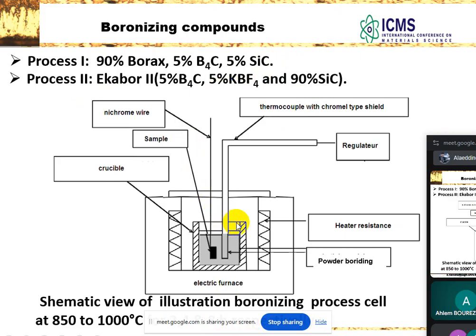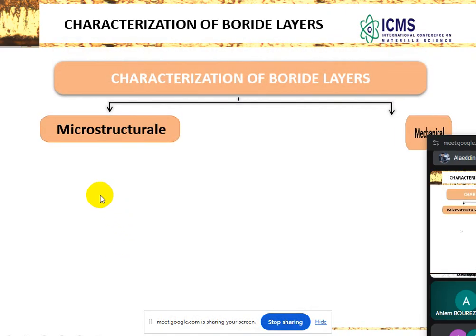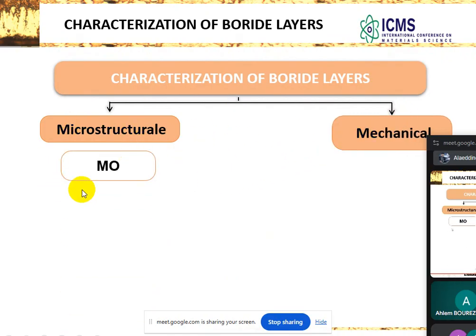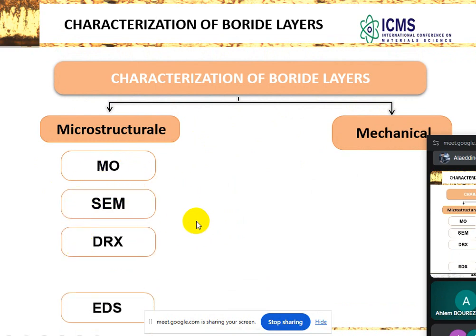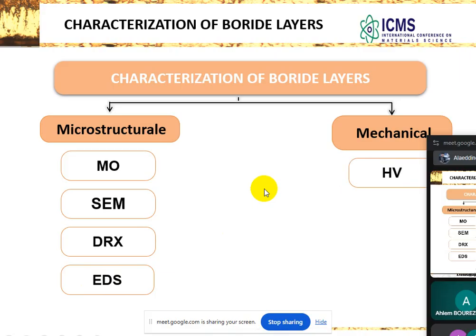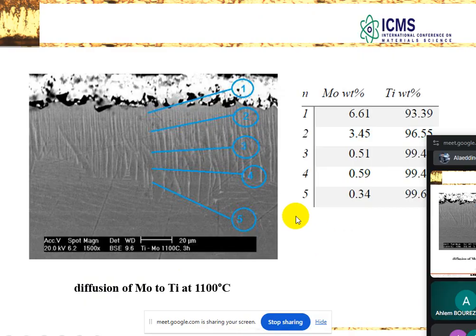This is a schematic illustration of the boriding process. This is our samples, and this is the electrical furnace. We put them in the crucible and in the furnace, and after the treatment we have some characterization of boride layers, microstructure and mechanical: optical microscopy, SEM scanning electron microscopy, X-ray diffraction, and also EDS analysis. As mechanical characterization, we have the microhardness and the fracture toughness.